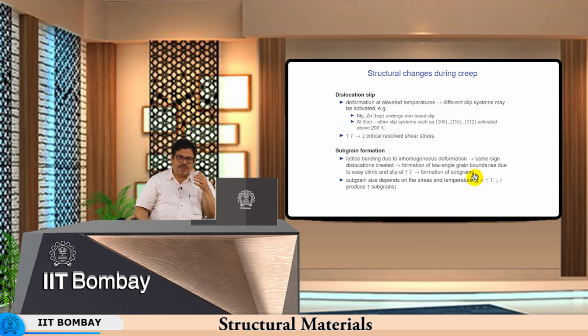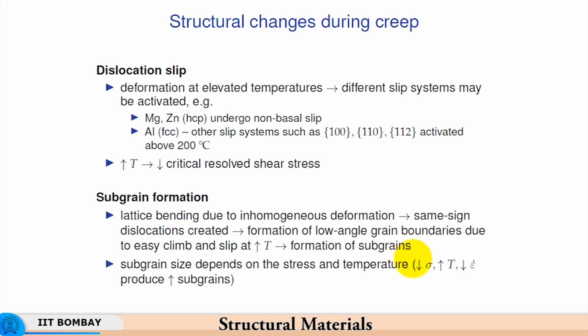So, as the deformation due to dislocation gets accumulated, same sign dislocations are created, then the subgrain boundaries are created, and these subgrain boundaries get developed into very low angle grain boundaries subsequent to recrystallization, and subgrain size depends on the stress and temperature. As the temperature increases, and stress and strain rate are lower, it produces larger subgrains. If the stress is more and strain rate is more, then the subgrain size would reduce, because the dislocation density will be more, the subgrain boundaries will be much closer to each other, and therefore the size of a subgrain would be much less in case of high stress and high strain rate.